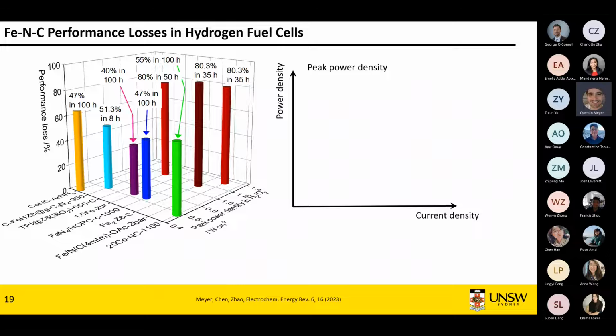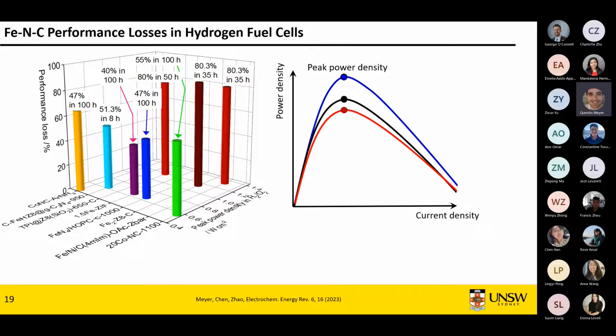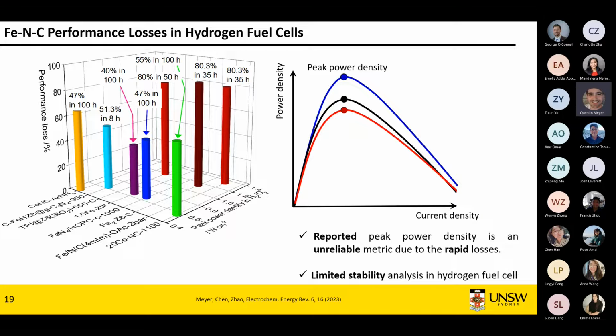And the problem when you have such stability problems is how do you actually look at reporting performance? So say you report the peak power density once. So you publish that right away. What people don't often tell you is what happened when they measured it a second time right away afterwards. That's what you get. You measure it a third time, that's what you get. You basically have a problem when it's very unreliable to actually capture performance, very difficult. You capture something as fast as you can, you publish it, you go to Nature Energy, they're completely okay with it. And then you just mention at the end that you still haven't quite fixed that.